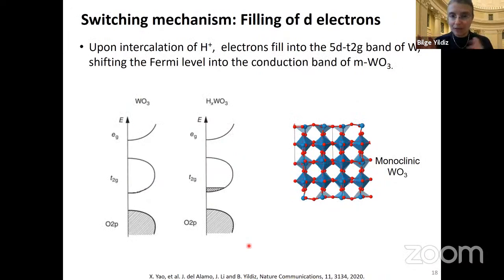So those are the characteristics that we have obtained from the device. And we like to understand why things work the way they do in my group. And so we have also performed a number of experiments and theoretical calculations to resolve how we are inducing this resistive modulation in tungsten oxide, based on its electronic structure as well as its atomic structure. And we can broadly hypothesize that when we are inserting hydrogen into tungsten oxide, hydrogen comes with a proton and an electron, and the electron fills into the 5d t2g band of tungsten that shifts the Fermi level up and increases carrier concentration and introduces higher conductivity, as long as we don't cause a phase change, right? At least within the same crystal structure. So let's see if that's what we find.